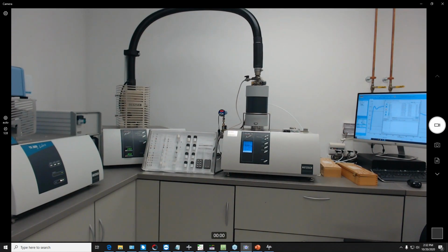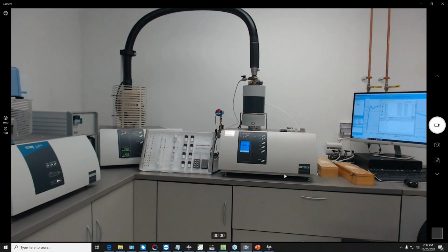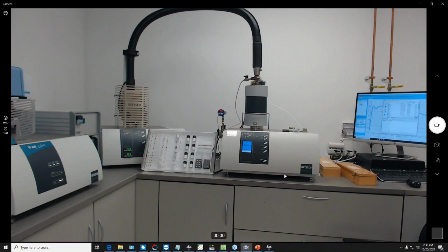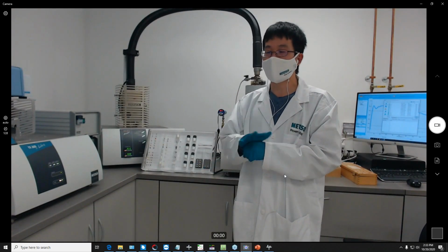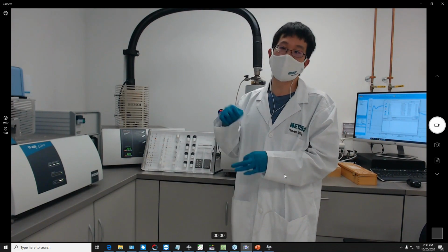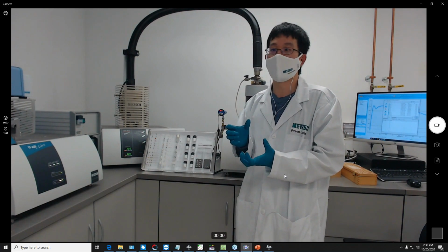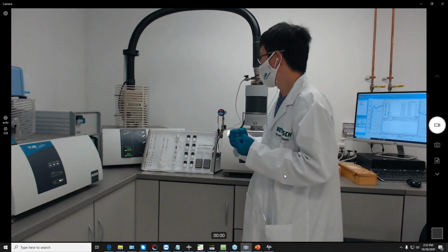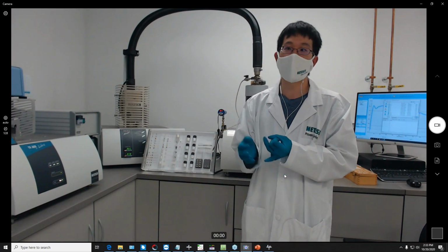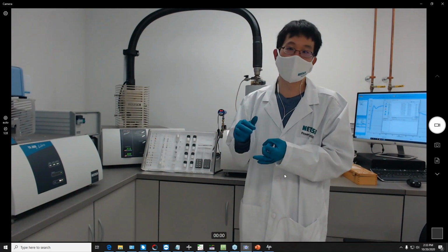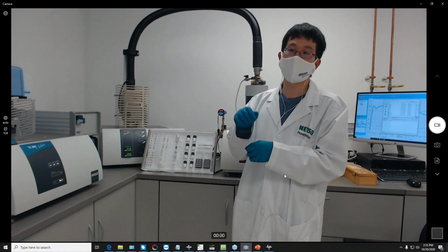The next question I have is, would a closed crucible be an oxygen or argon deficient environment regardless of your flow condition? All of our DSC crucibles have the ability to have a pierced hole on top, so that doesn't necessarily mean your measurement has to be sealed. For example, our aluminum low temperature crucibles that go to 600 degrees Celsius, we can crimp them shut, so you can have a sealed crucible in that case. But you could also puncture a hole through the lid of the aluminum, and then you would be exposed to whatever purge gas environment you are running. All of our high temperature crucibles, the aluminum oxide and the platinum rhodium crucibles, do not seal. The lids just rest on top of the crucible, and all of those have a pierced hole.